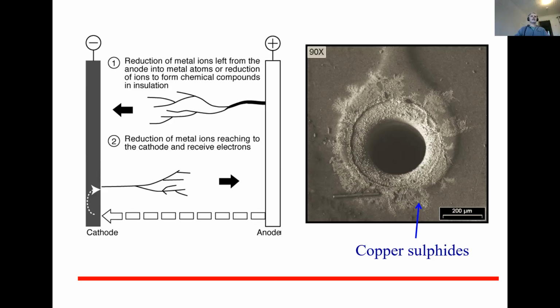So what we know is that our corrosion products can either grow from the anode, like here. This is a plated through hole in a printed wiring board, and around that plated through hole, so the electrical connection between top surface and bottom surface or inner layer in printed wiring boards. So this is a picture from the top. So you see that around this hole, there are these tree-looking structures, which are, in this case, copper sulphides.